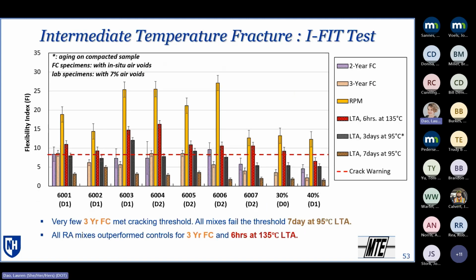Now looking at intermediate temperature fracture, this was done with the IFIT tests. With the IFIT, we don't have a way of converting for air voids. So anything with the field cores, those are in-place air void contents, and the lab mixes are 7%. So you can't do direct comparisons there, but you can at least compare to the controls. This does have an additional aging condition. Illinois DOT did these tests and they've got their own aging protocol of 3 days at 95 degrees C on a compacted specimen. So we've got that included in there.